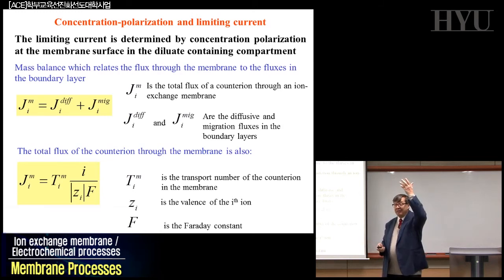So you are increasing the ohmic resistance of the system a lot. That is the limiting current. When you arrive at this point, approaching zero concentration at the interface, that's the limiting current. You must be careful, because if you want something going across, instead of increasing pressure you are increasing the difference in potential, trying to increase the electrical field. Be careful, because if you do this, and people have been trying it, you have another negative phenomenon: water splitting. If you give too much energy to the system, the molecules of water split,